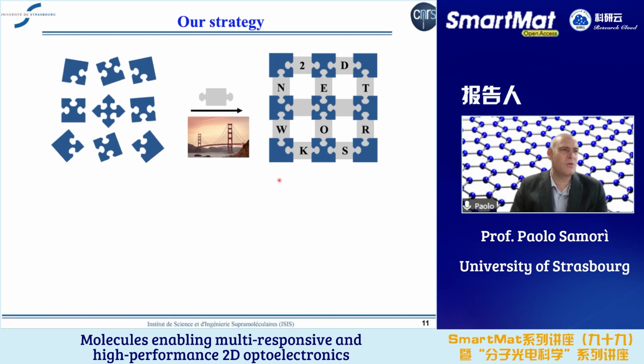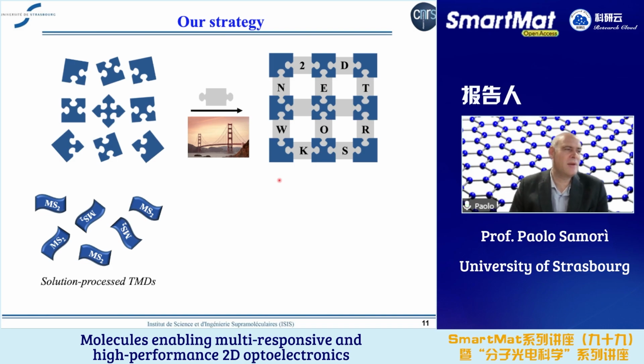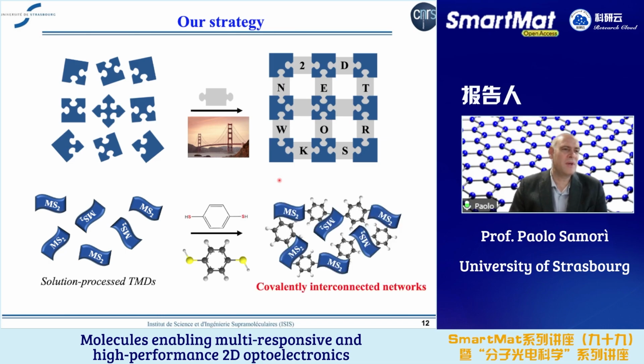And actually what we have been doing is to take this liquid phase exfoliated MoS2 and use a doubly thiolated molecule that can act as a bridge. This molecule that we chose is the benzene dithiol, and therefore the core of the molecule is semiconducting. And so in this way, we can interconnect covalently the flakes to create a network. At the same time, we not only create a network, but we also heal the sulfur vacancies that we have on the MoS2 surfaces.